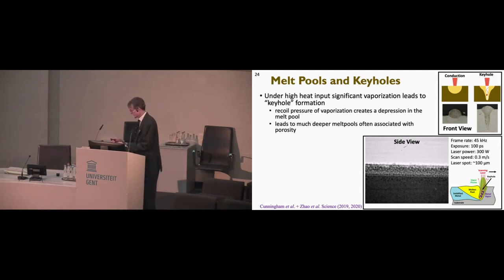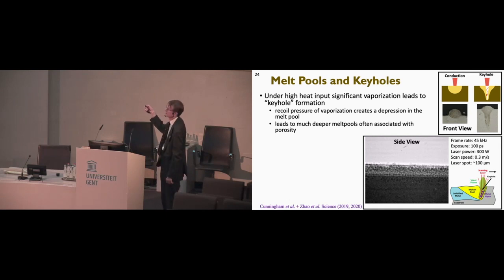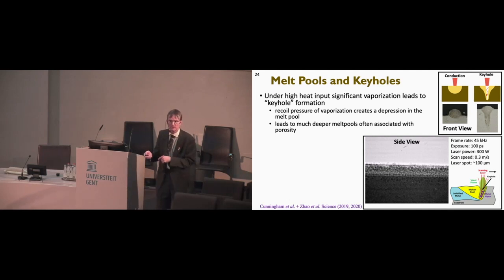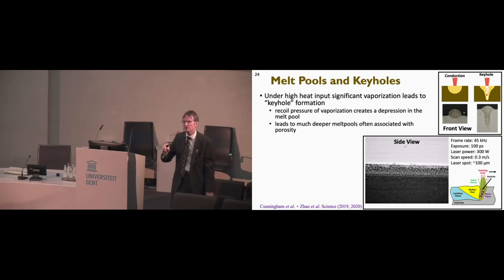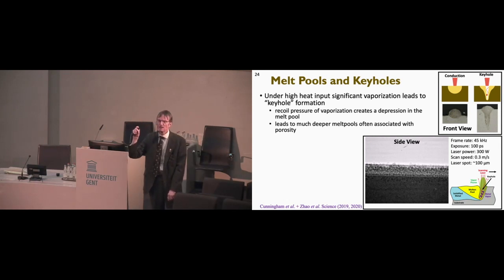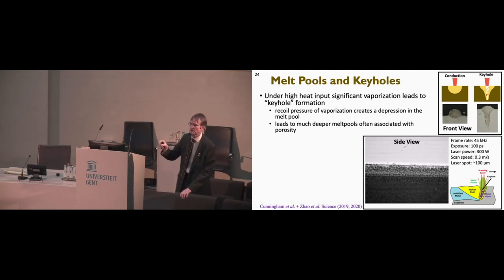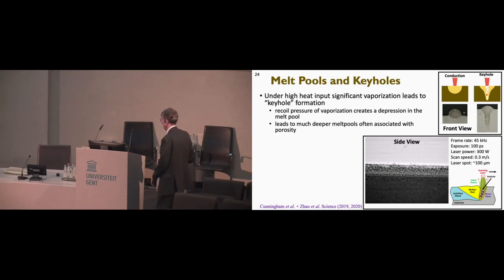And the point of the little diagrams up here and the micrographs is that if you do not have too high a power density, then you just have conduction of heat. And the melt pool that you get is a section through a circle, a semicircle in cross-section. However, if the power density goes too high, you start boiling the metal. So I'm going to show you the result of that. And the laser beam drills its way into the metal. Very important for deep penetration welding.